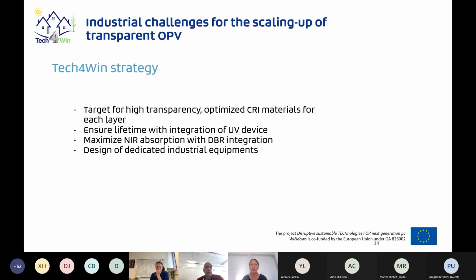So it's really a big challenge, and a really interesting and enthusiastic development for industrial partners as well. To answer a few of these challenges, the Tech4Win strategy is to target high transparency, optimized CRI materials for each layer. The strategy is also to ensure lifetime with the integration of a UV device. Lifetime for OPV is good these days, but if we need to really target the lifetime of a window without any failure, it's good to assess this lifetime strategy really early in the project.